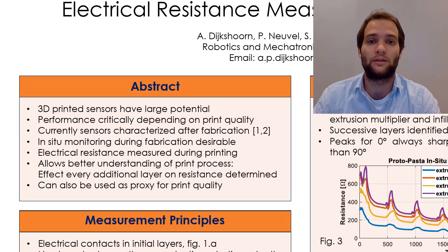What we did is that we performed electrical resistance measurements during printing, so in situ, to monitor the resistance. And in this way, it allows us to get a better understanding of the printing process. So the effect of every layer added on the sample, the effect on the resistance can be measured in this way. And this can also be used as a proxy for measuring print quality.